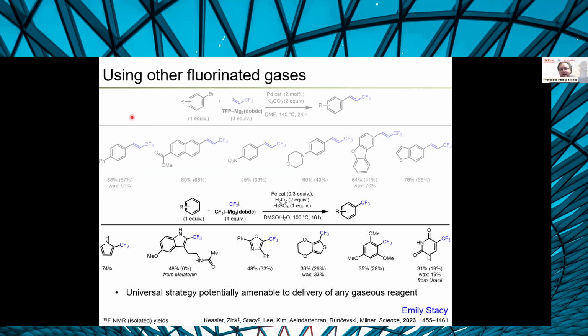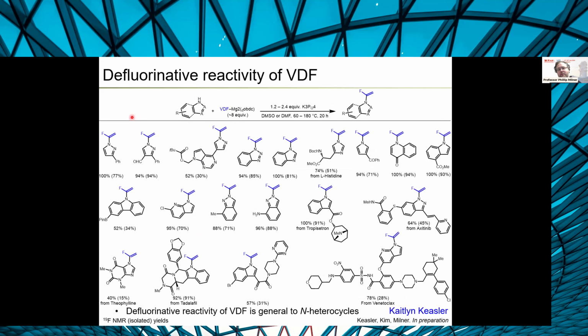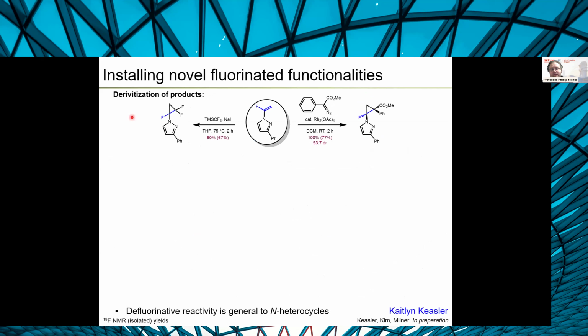And what we have started to do now is use this platform as a way to explore the reactivity of gases that have really been overlooked in the synthetic community. So for example, Kaitlyn, as I mentioned, has found that vinylidene fluoride is surprisingly electrophilic. Well, it actually reacts with a range of nucleophiles, not just palladium catalysts, but also nitrogen heterocycles here, which allows us to actually make a range of different N-fluorovinylated compounds here, even from some particularly large and complex molecules here, using these very simple metal-free conditions. And these products themselves are quite useful.